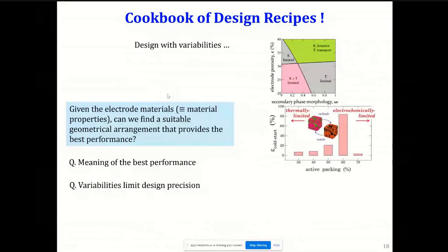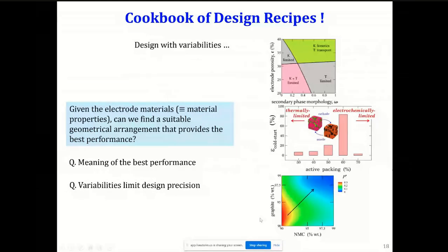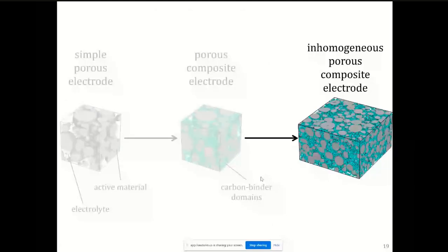We can do design which is targeted at the heat generation of the electrodes, right? So think of just by making microstructural changes in your electrode, you can control the amount of heat your battery is going to generate, and you can get around quite a bit of external cooling requirements that you would have to put in. Another thing you can do is you can also design for degradation, because the processes that degrade these batteries over time, things like plating and SEI, they are fundamentally transport processes. So they would have an effect based on what your microstructure is, right? Now, let me pause a few minutes here and then get on to the inhomogeneous part.